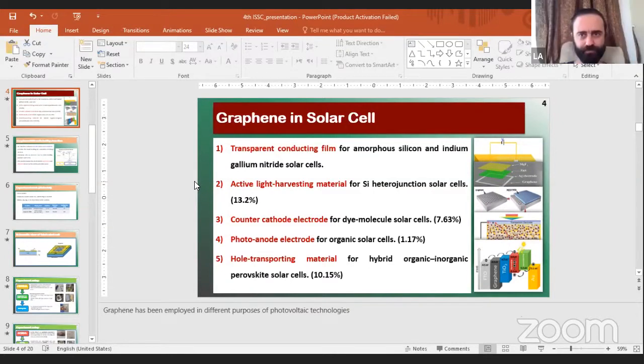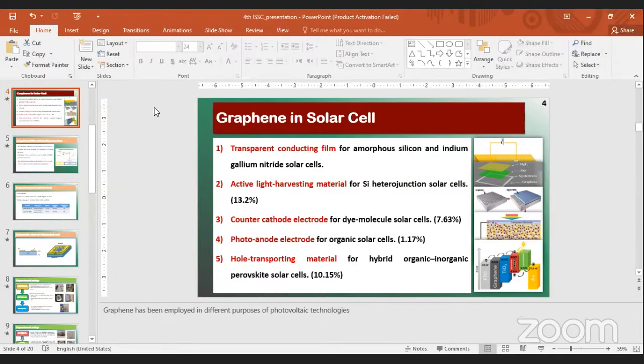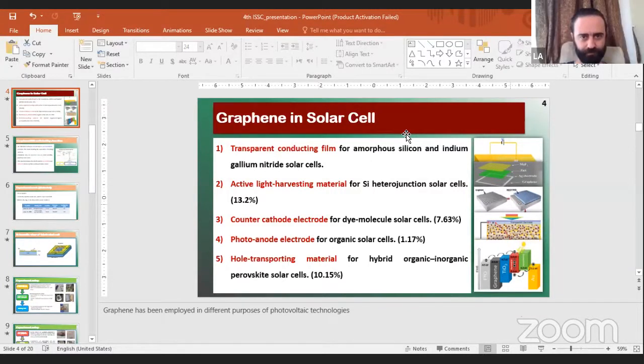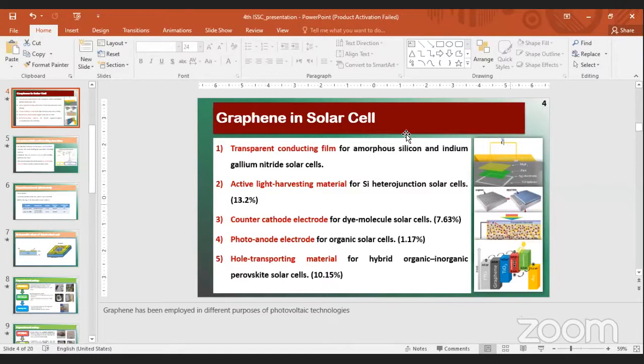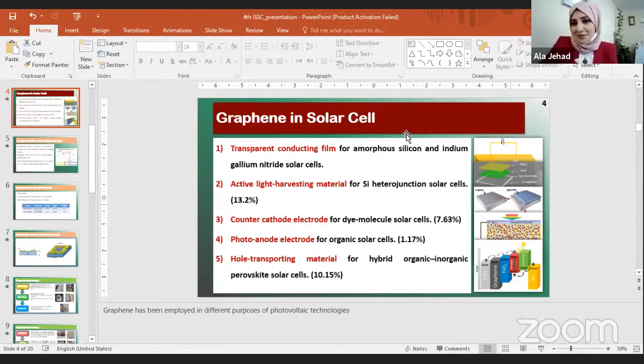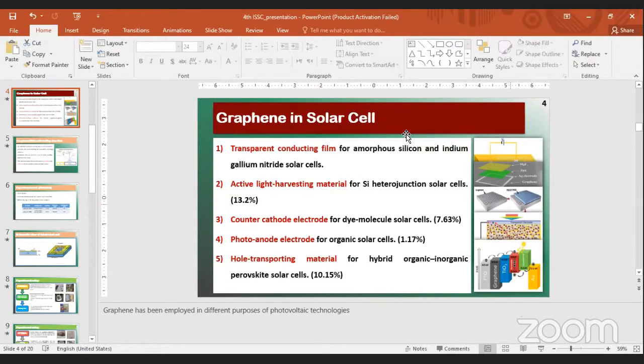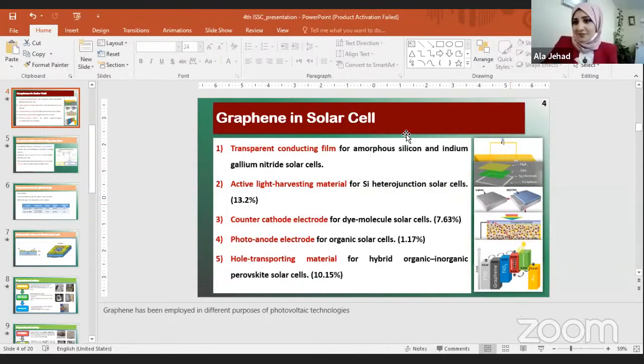Okay, more questions? Actually, I have a suggestion to remove the PMMA residues. Maybe you can use a lower concentration of PMMA instead of using 4% in chlorobenzene. You can use like 1% chlorobenzene. And also for the heat treatment after you coat your samples with PMMA, maybe without heat treatment you can remove it more easily. Just try this. Probably without heat treatment after the PMMA coating, it will be easy to remove all the PMMA residue. Okay, I will. Thank you so much.